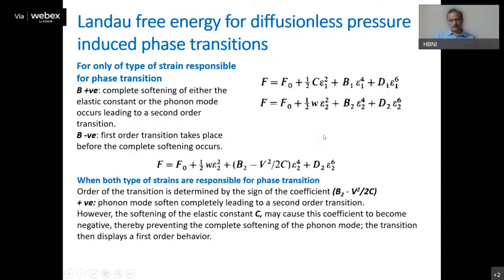So in case of pure homogeneous strain related phase transitions, this expression describes the phase transition. As we discussed in case of Devonshire theory, this B has to turn negative in order to make it a first order phase transition. But if we have a B positive, then how will this phase transition happen? In this case, this C starts going down, so it softens. So elastic constants soften, and it is the softening of elastic constants that leads to this phase transition. So basically phase transitions would be of second order, continuous phase transition.